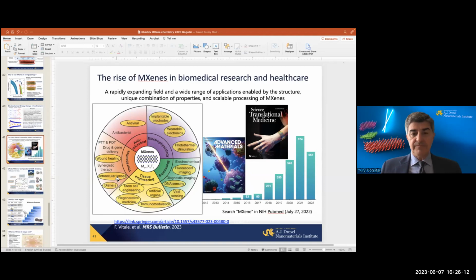However, keep in mind that there are chromium MXenes, which people are still trying to make. We can make chromium titanium carbide MXene, which may produce, for example, soluble chromium compounds. Vanadium-based MXene can also produce some soluble compounds. And no one really looks systematically at all the possible treatments. For example, if you have chlorine on the surface and chlorine-titanium bonds start hydrolyzing, producing active chlorine, I think this may be responsible for antibacterial and antiviral properties, but it may also cause an inflammatory or toxic response. So you cannot bluntly assume that every MXene is safe to use, and we should treat them as any other new materials. Yeah, thank you so much for the answers.